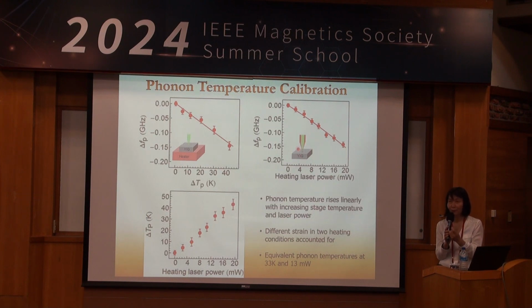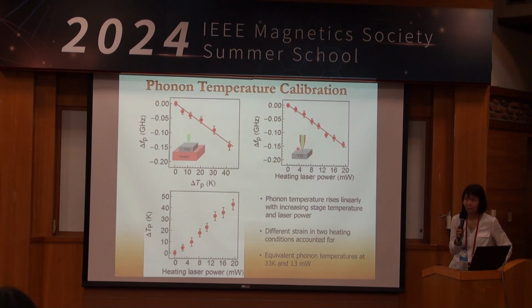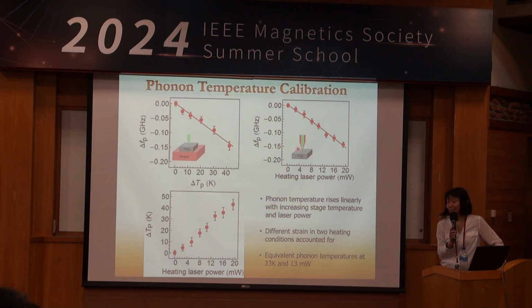Okay. So, in fact, when you're searching for low damping insulator, you want to look for a situation where phonon and magnon couple weakly. Otherwise, phonon would dissipate, with the cost of dissipation. But that would only work for an insulator, because if it's a metal, you have electrons as well. Metal is so messy, because electrons are a heavily damping mechanism for both energy and spin current. Right. Okay. I'm still probably going to be thinking about it for a while, but it's interesting.